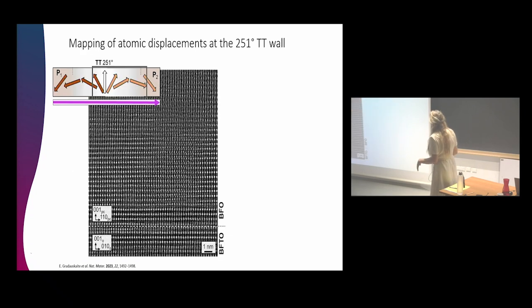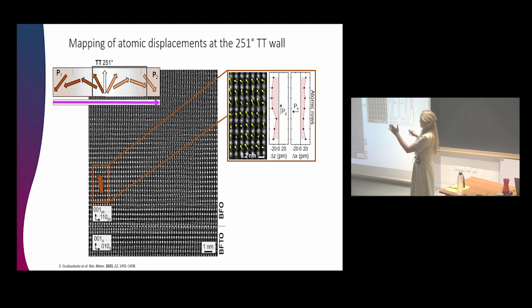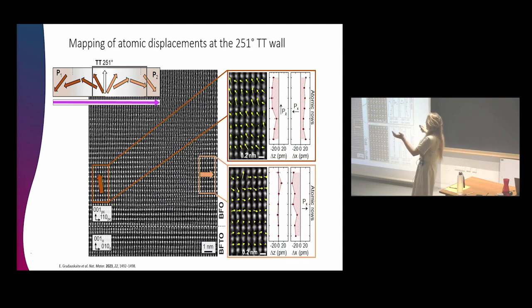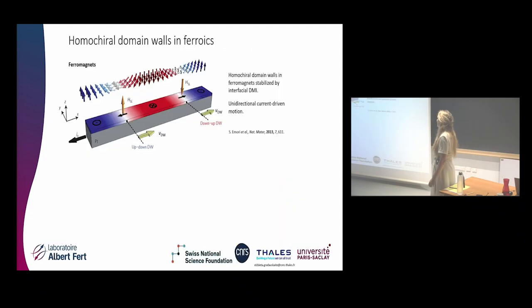And we could even see it in our atomically resolved STEM. We could see that we have areas on this tail-to-tail wall that are pointing upwards, left, and some of them are pointing right. So maybe you can also see some strain at the wall and some rotation of polarization that seems to be consistent with this. And once again, just to reiterate the message, in ferromagnets that's quite well known. In spintronics, homochiral domain walls are usually stabilized in ferromagnets by interfacial DMI, and that's usually what enables the unidirectional current-driven motion.